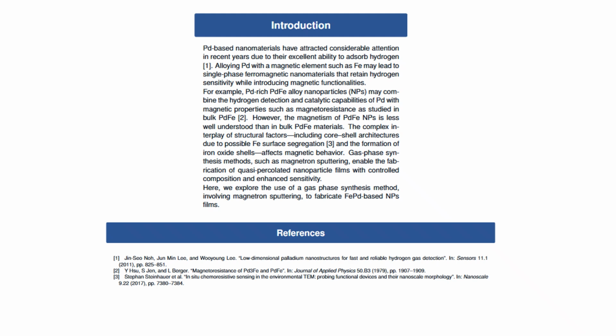However, the magnetism of palladium iron nanoparticles is much less understood than in bulk materials. One important factor is the possible formation of core shell architectures due to iron surface segregation and iron oxide shell formation, which can strongly influence the magnetic response. Gas phase synthesis methods like magnetron sputtering allow the fabrication of quasi-percolated nanoparticle films with controlled composition and potentially enhanced sensitivity. In this work, we use such a method to fabricate iron palladium-based nanoparticle films and investigate their structural and magnetic properties.